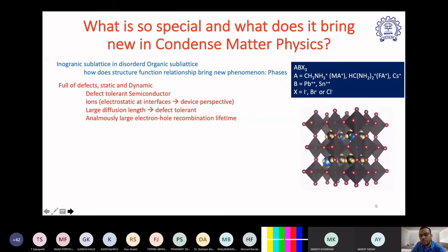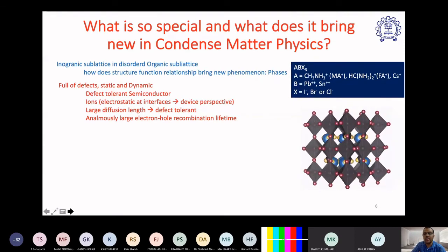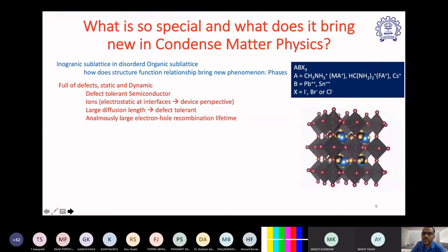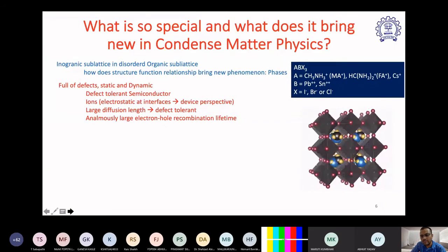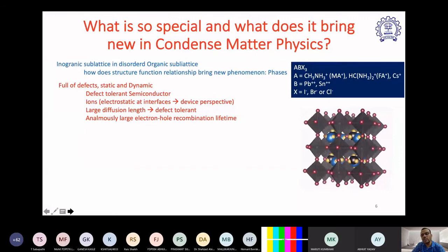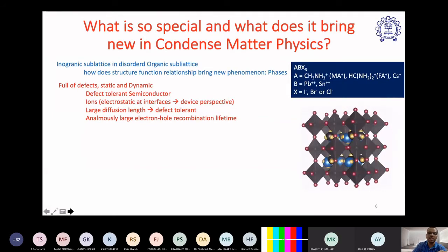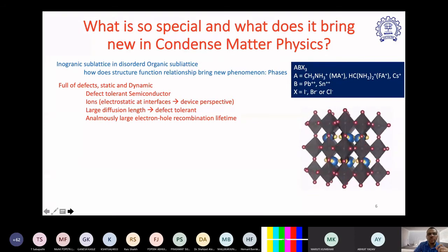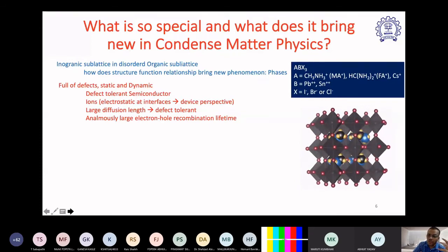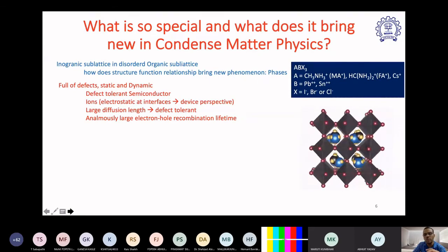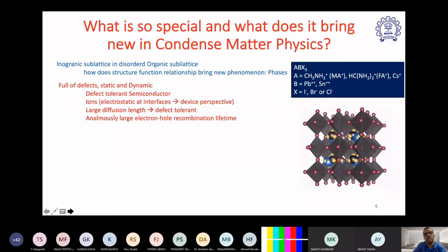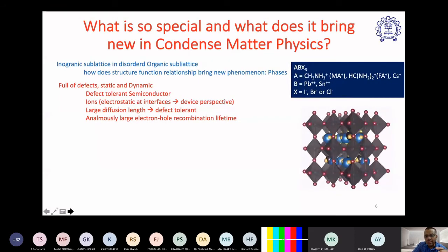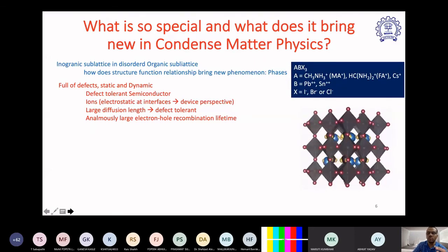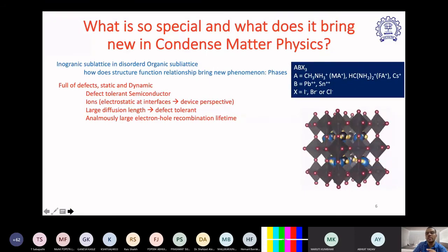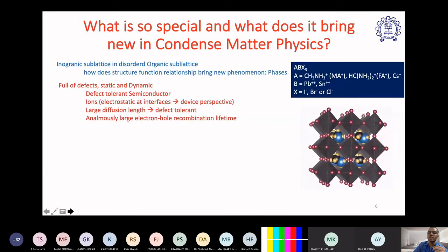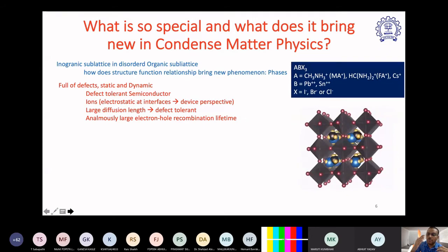As I was telling, we do all these depositions via solution process, and furthermore, we know that every PbX6 is associated with one disordered organic sublattice. You have an inorganic sublattice and a disordered organic sublattice. So this disordered organic sublattice is continuously moving with respect to that open space, and that creates lots of defects. So halide perovskite, despite having a very good crystalline structure, is known to have lots of defects. Not really static, but most of these defects are dynamic in nature, because if you give a little bit of temperature, the vibrations of the molecules will increase. The molecule becomes much more active with temperature, and then you find that the perovskite will have more defects, and you will see all those defects playing a role in temperature and time dependent PL decay.